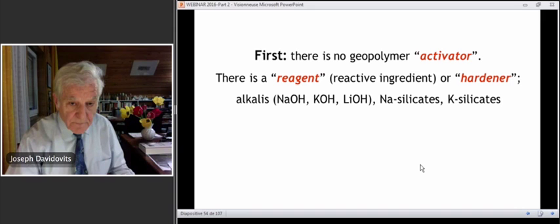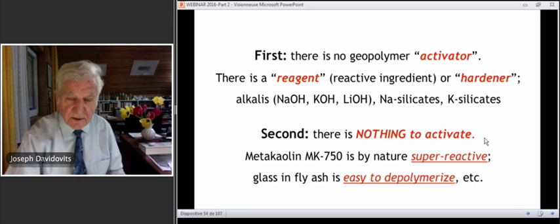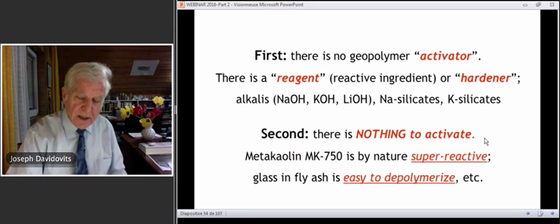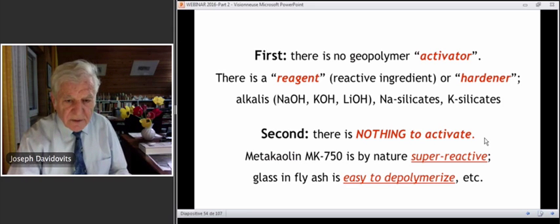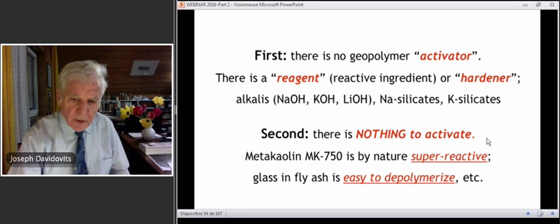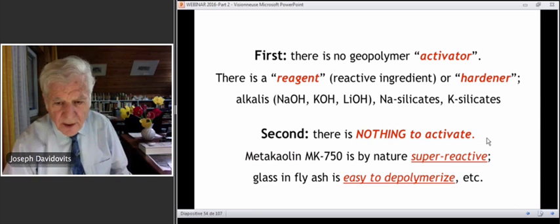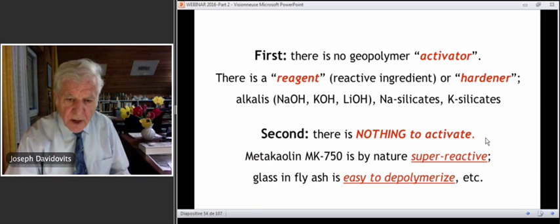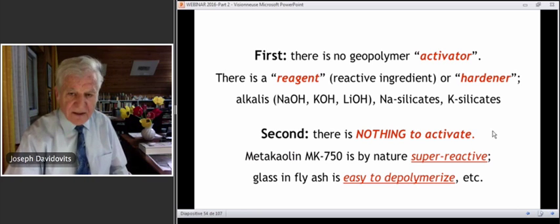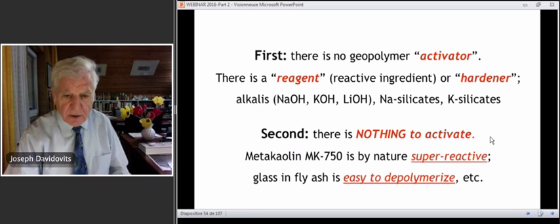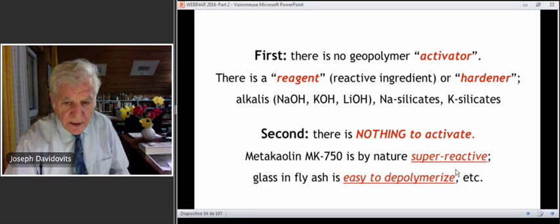Why? Because there is nothing to activate. This is a wrong terminology that is dating back to alkali activation of slag from Purdon in 1940, when he took slag and added 1.5% of NaOH in order to see if the slag was good and reactive. So he said, I am activating my slag because it is inert otherwise. For us, we don't have to activate. The metakaolin is by nature super reactive. You don't have to put NaOH in order to have a metakaolin super reactive.